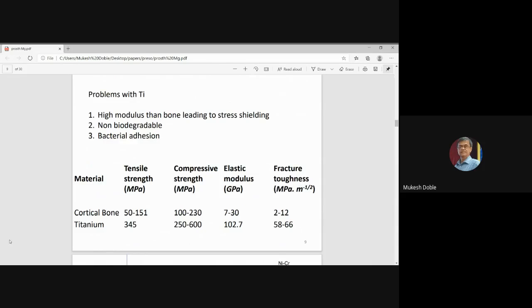As you can see, the tensile strength of titanium is 345 megapascals, as against cortical bone, which is 50 to 150 megapascals. Again, the compressive strength of titanium can be 250 to 600 megapascals, whereas the compressive strength for bone is 100 to 230. Elastic modulus for bone is 7 to 30, titanium is 102. Fracture toughness is 2 to 12 for bone, titanium 58 to 66. So titanium has a very high modulus when compared to bone.